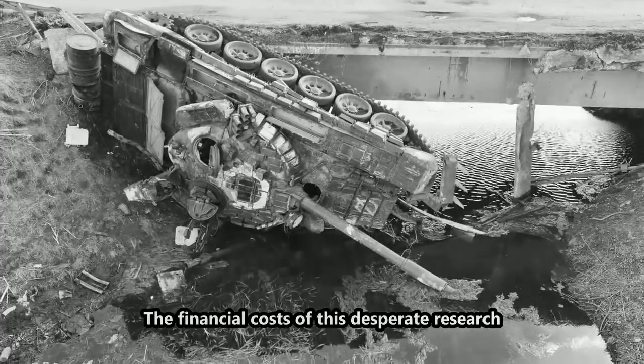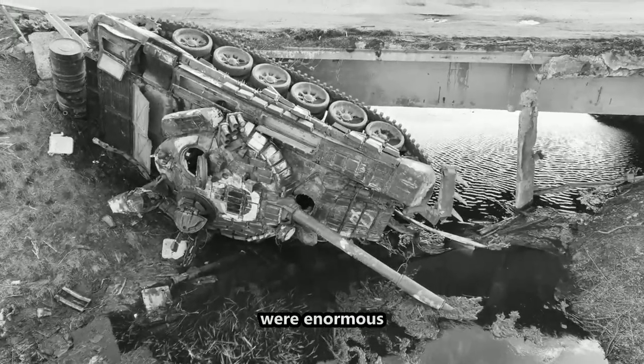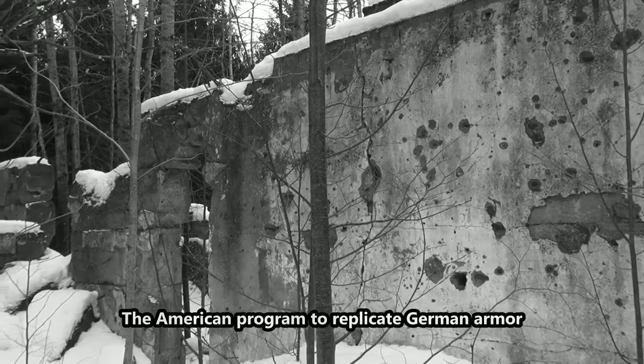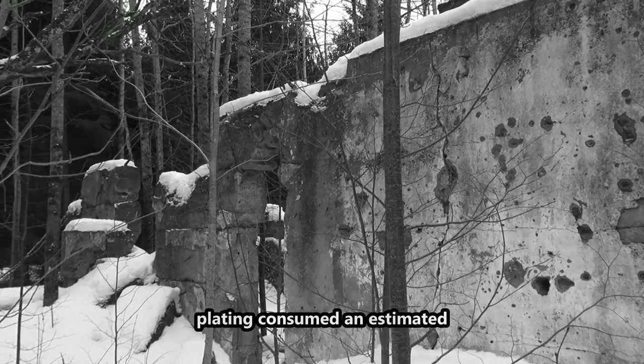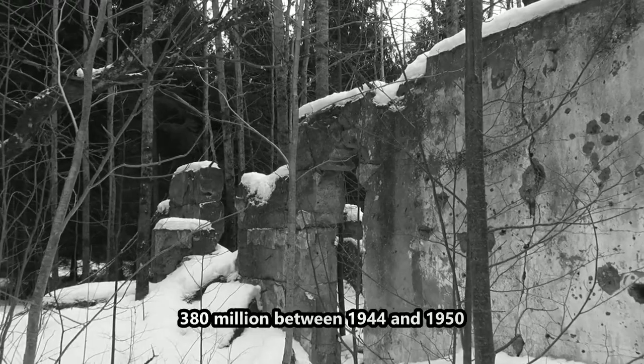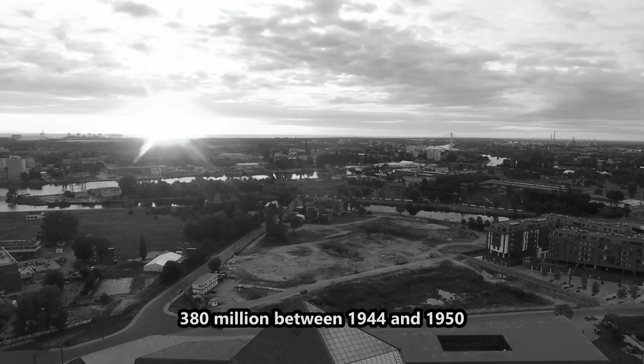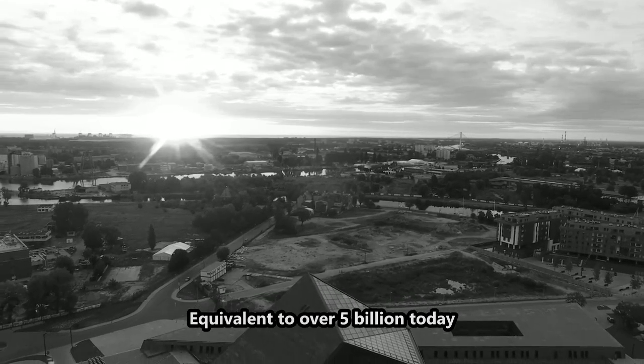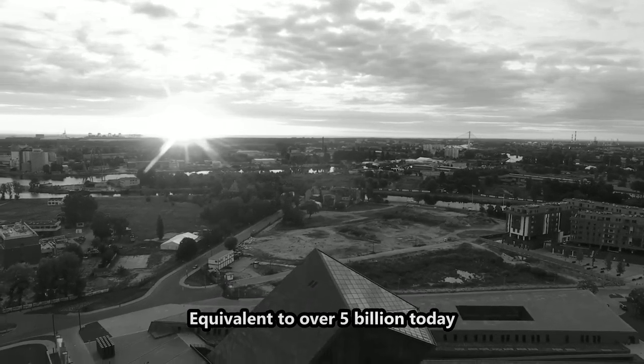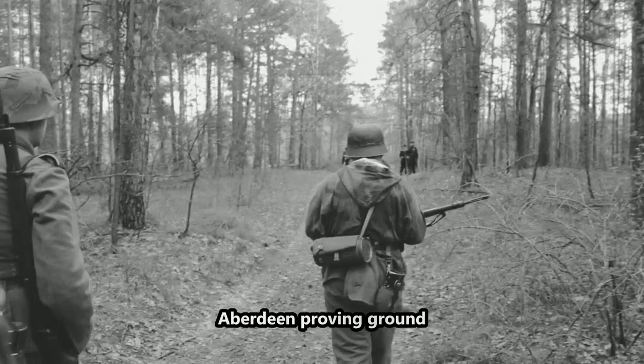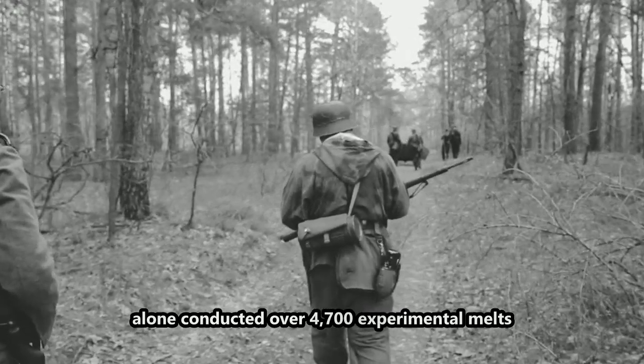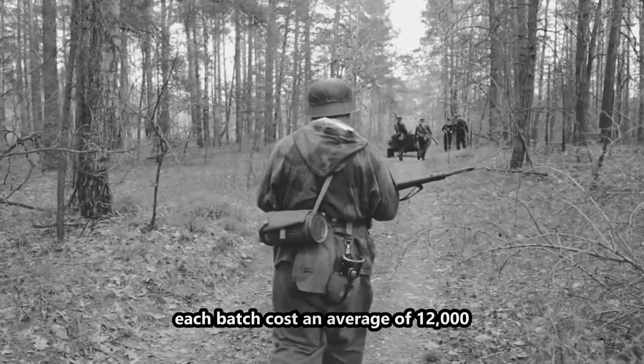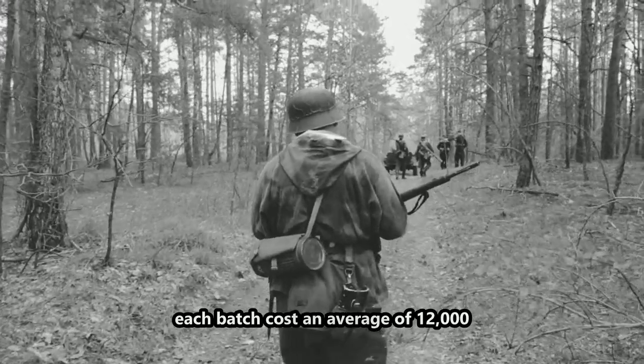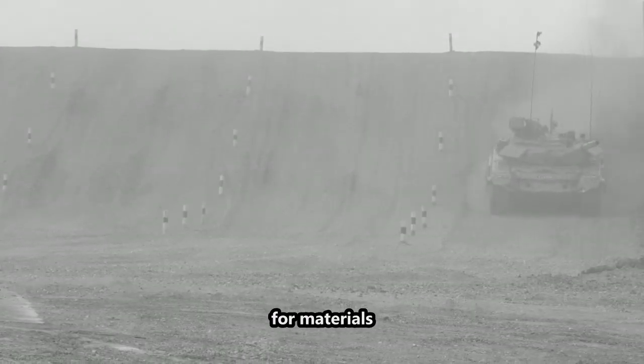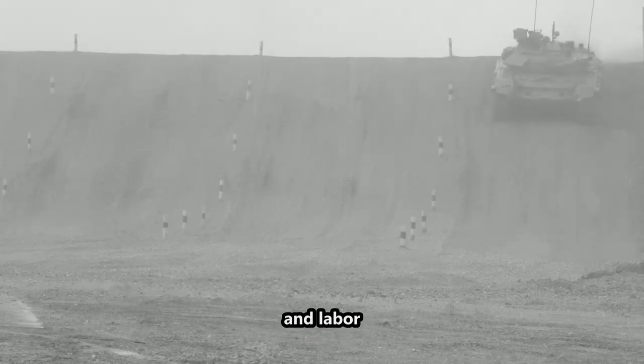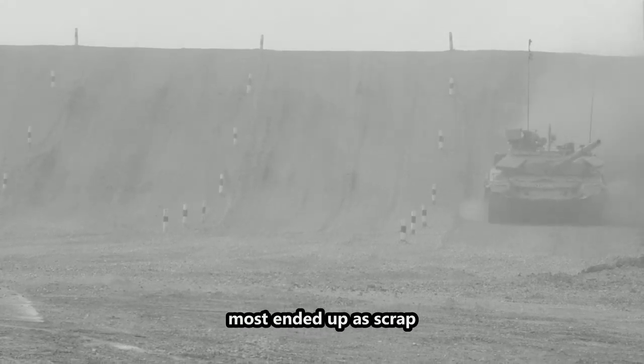The financial costs of this desperate research were enormous. The American program to replicate German armor plating consumed an estimated $380 million between 1944 and 1950. Equivalent to over $5 billion today. Aberdeen Proving Ground alone conducted over 4,700 experimental melts. Each batch cost an average of $12,000 for materials, energy, and labor. Most ended up as scrap.